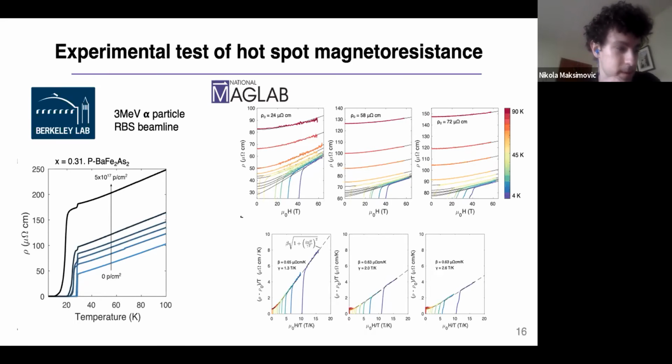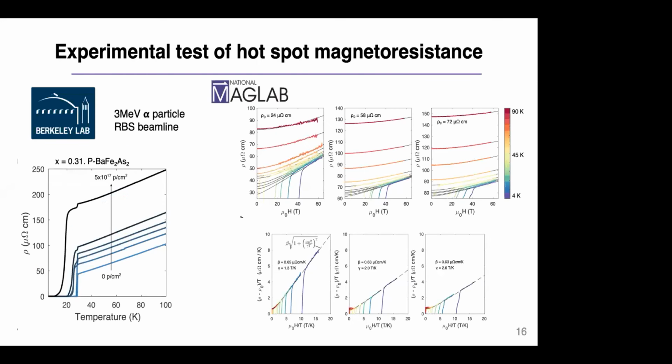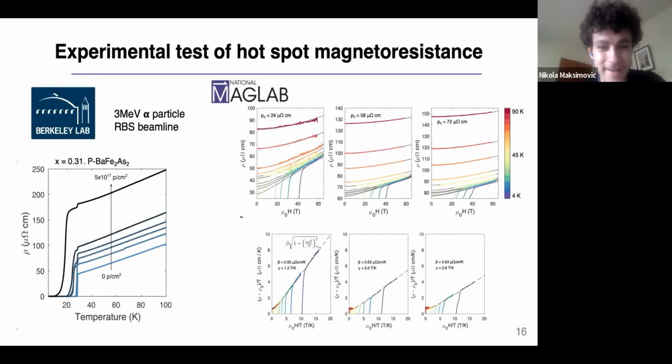You need to, I think it's important to consider what the Fermi surface and scattering rate look like. Also, if you have very clean samples, the cold spots of the Fermi surface can give a significant contribution. In the cuprates, we did a lot of work dirtying the samples, and when you dirty them, they are still H square. Okay, that's interesting. It might be interesting to compare.